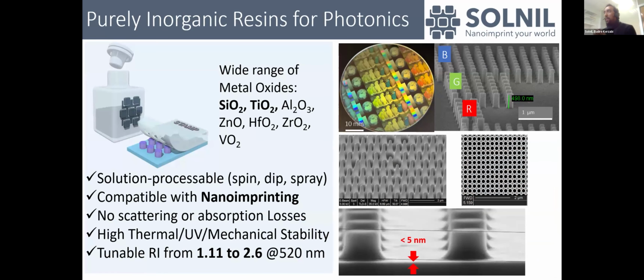So what are the materials that we are developing at Solnil? What we developed is a sol-gel chemistry that allows us to deposit a wide range of metal oxides, silica, titanium mainly, using simple liquid deposition processes, such as spin coating, dip coating, and spray coating. And using these simple processes, we can deposit high quality optical coatings, which also have the benefit of being compatible with nano-imprint lithography. So it could be used both to make optical coatings or nanostructured surfaces.